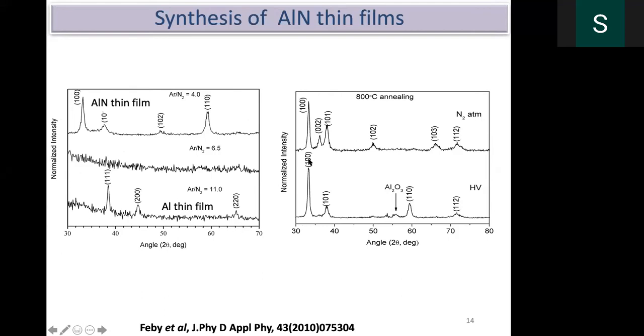We just annealed at two different conditions, one in high vacuum and another in nitrogen atmosphere, at a temperature of 800 degrees centigrade. You can see that in high vacuum annealing, high vacuum means 10 to the minus 6 millibar, not more than that, a small alumina hump has been seen, but it's not a real peak unless we go and do the XPS analysis.